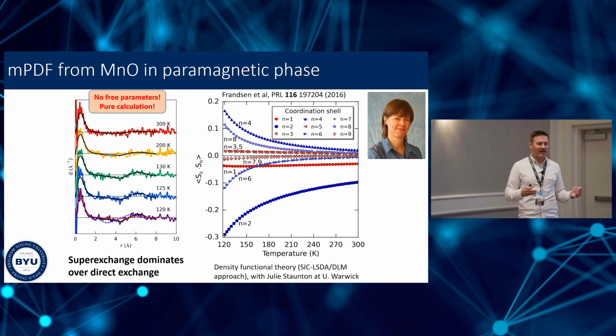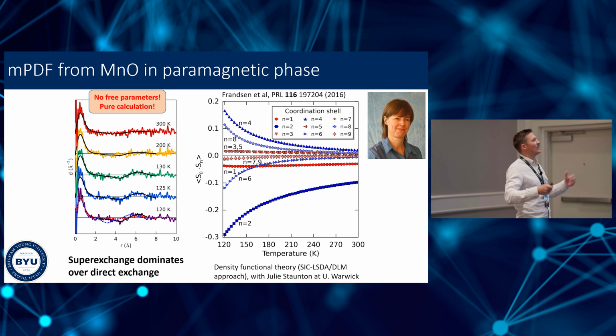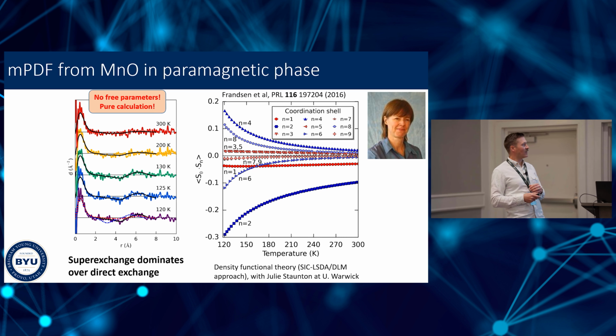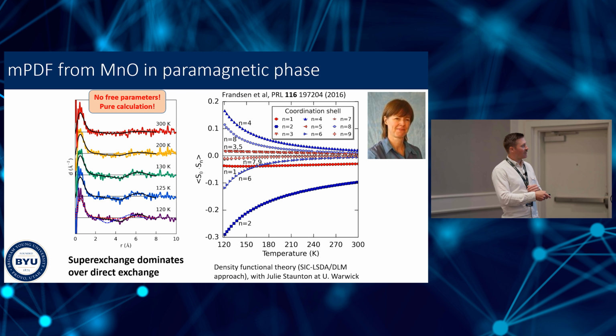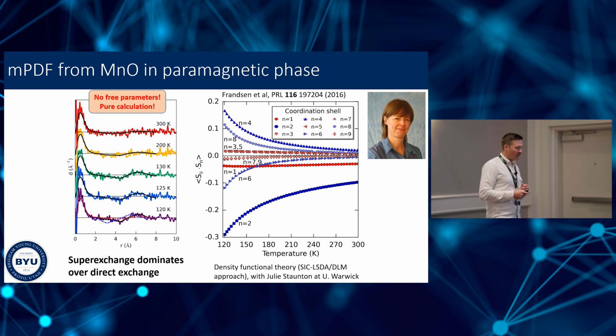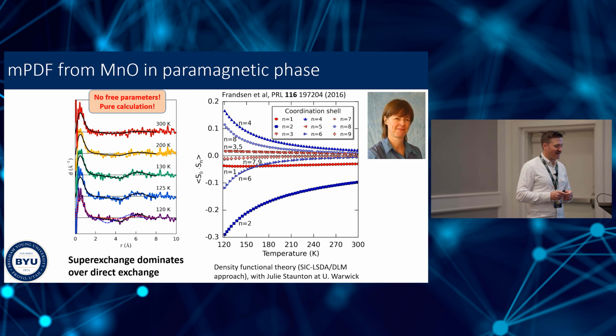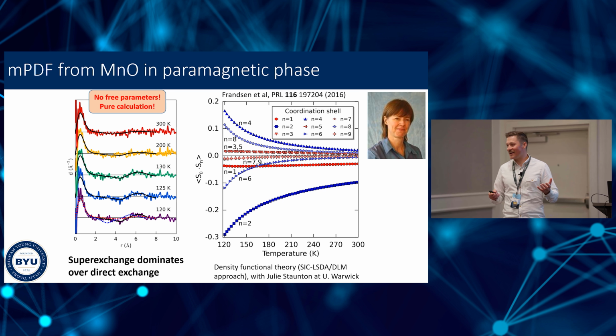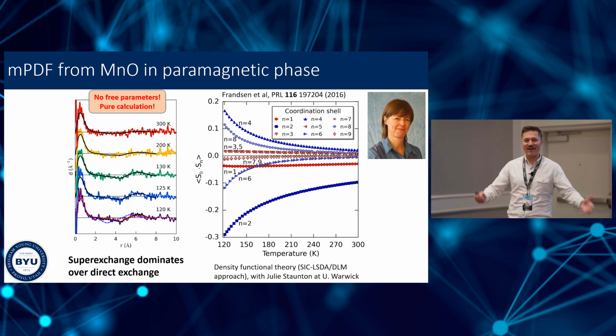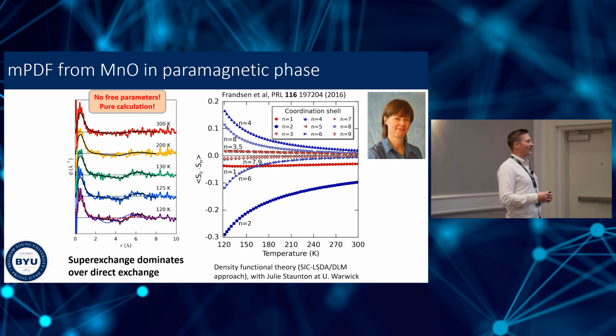When the average magnetic structure has disappeared, there are no long-range magnetic correlations at those temperatures. Nevertheless, these well-defined local correlations contain important information about the material. Okay, so this was our first foray into magnetic PDF analysis, and it worked well enough that I was willing to try to make it a significant part of my career going forward,